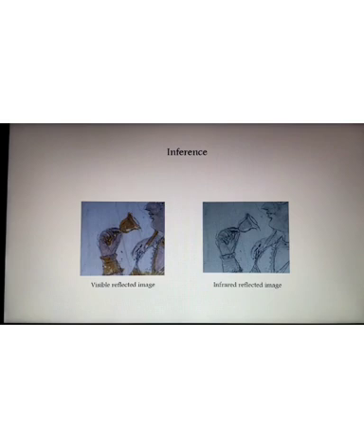The following inferences can be made from these imaging techniques. In the infrared reflected image, more prominent outlines are visible as compared to the visible reflected image as a result of IR photography, which is used to detect the underdrawings. The underdrawings are usually made of carbon black, which has a property to absorb the infrared radiation. Thus, the infrared reflected image shows more prominent outlines.